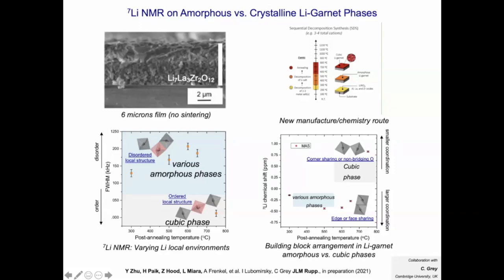And only if we crystallize to the cubic phase can we see a classic corner bonding of the bonding units. However, for the various amorphous phases, we see it's a non-Zachariasen glass, because it can bond over the faces and edges even for the building units. And it forms, depending on which amorphous phase you are in, a different condensation of the overall structure. So it's, in some analogy, very different to LiPON, and it's another type of non-Zachariasen glass.